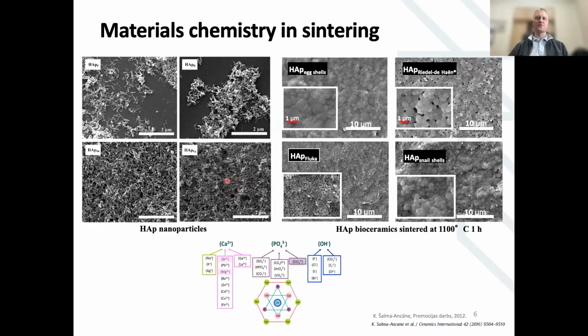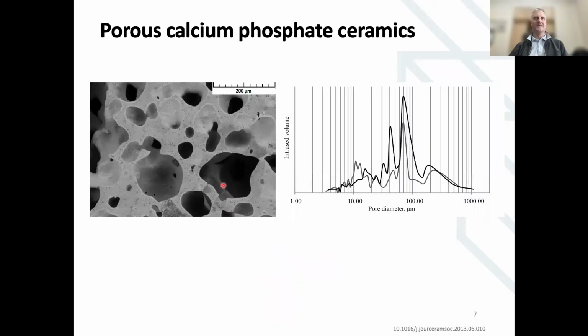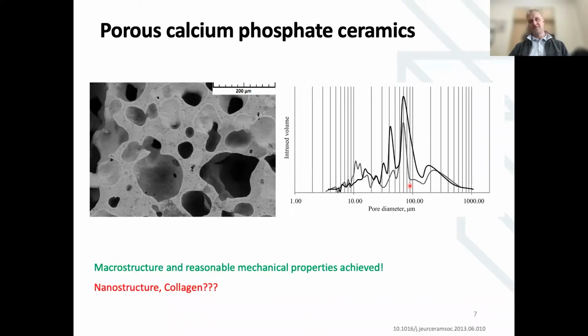So moving further, finding the proper way to shape those nanoparticles, we ended up with one very nice technique to sinter porous ceramics made of hydroxyapatite. The porosity is good, close to the bone one, and the pore size is also quite good. We have a macrostructure. We can make quite big pieces of the material. We have more or less reasonable mechanical properties. Of course, they are not even close to the bone. The compression strength for bone is 200 megapascals, so we are at least 4 or 5 times below, meaning about 40, 50 megapascals. But that is at least something.